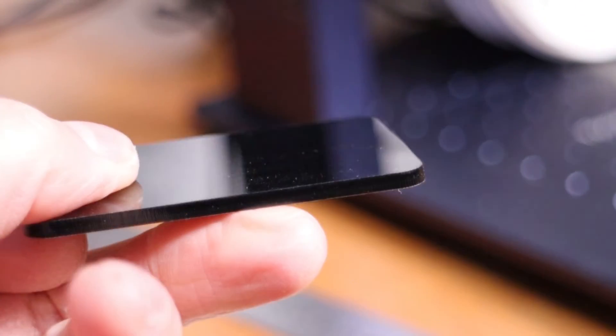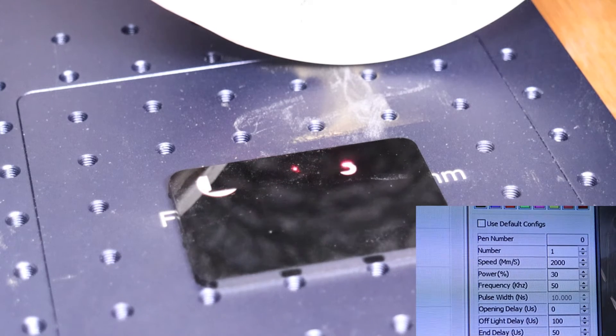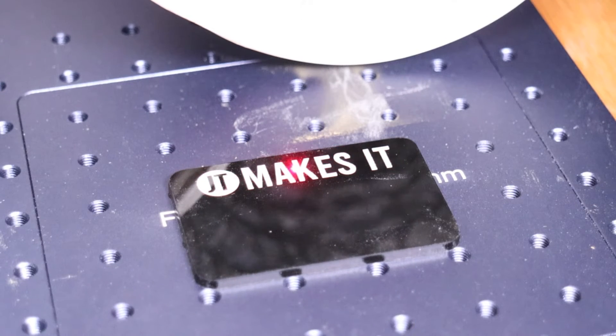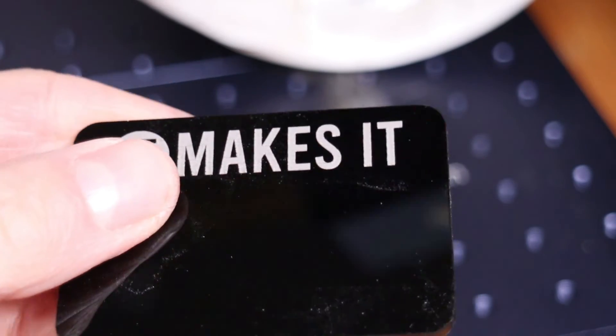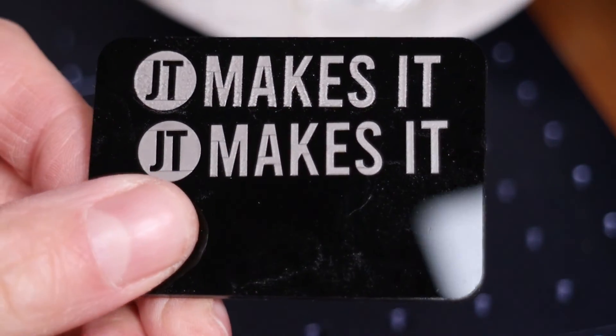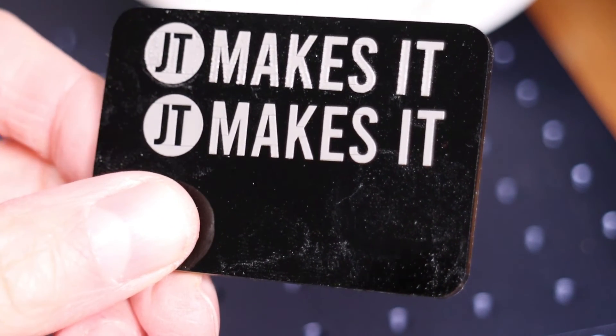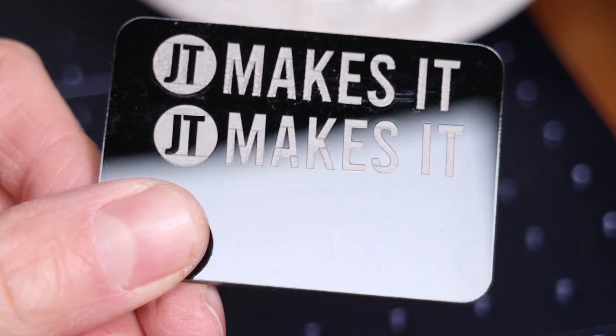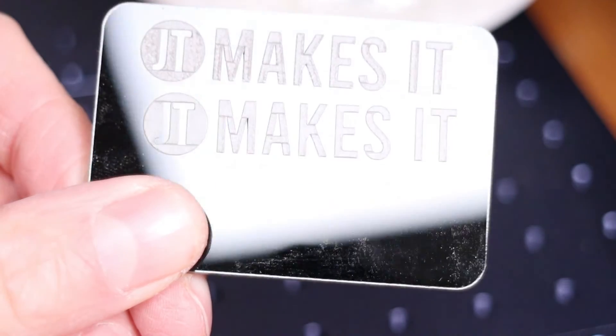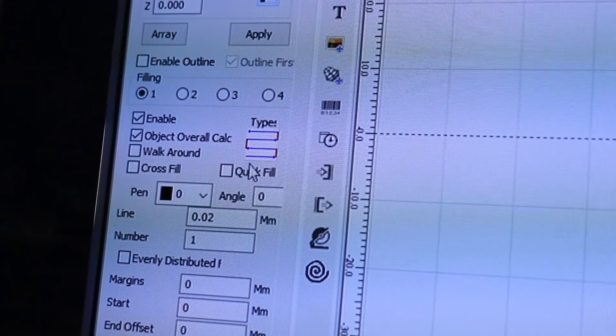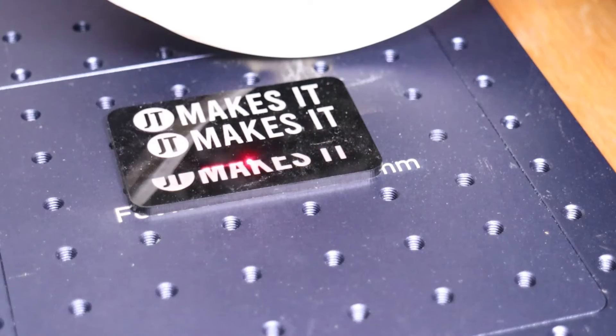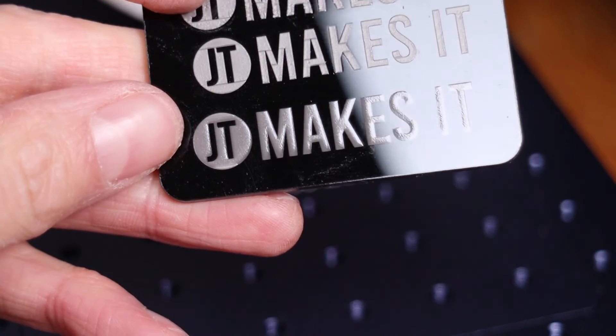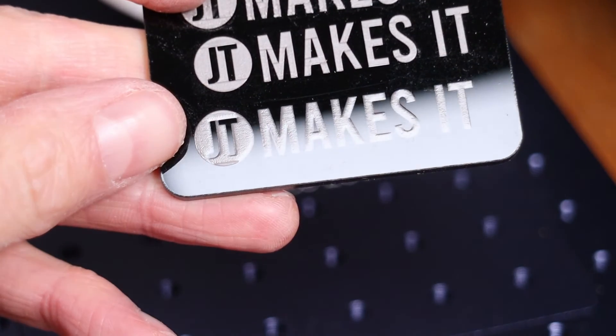I went to engrave my logo on black acrylic. The engraving was great. I tried again by tweaking the settings a bit. The only problem I noticed is the fact that it did not engrave the shapes in one go, and consequently, the surfaces are not evenly filled due to uneven melting of the material. I had to change the fill pattern to this one, and then it engraved it in one go, and the result was perfect. Engravings on black acrylic really pop out and are very durable.